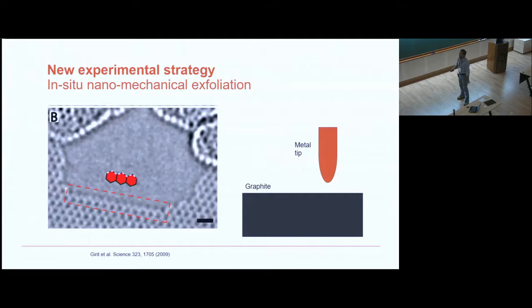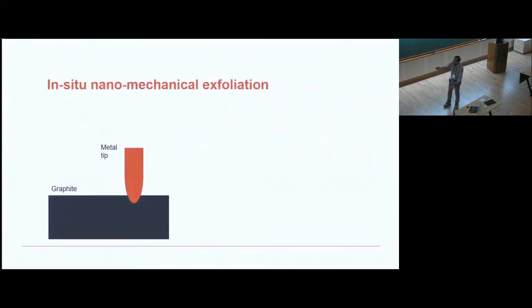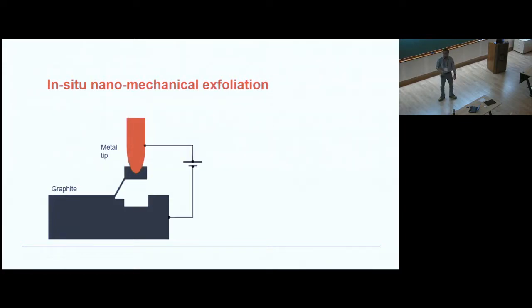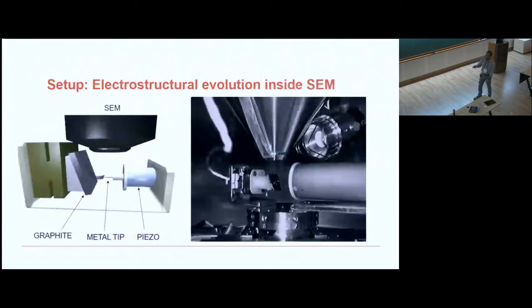We did a very simple experiment. We took a metallic tip, and we punched it into graphite like this. And then we pulled it up. That's it. We tore it. And while tearing it, we looked at its electrical resistance, and that gave us very interesting results. I'll show you in a minute. There were a lot of experimental details in it. This experiment took nearly three years, but I'm not going to go into that, but I'll give you the results.